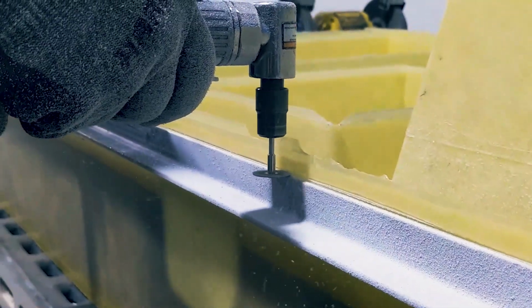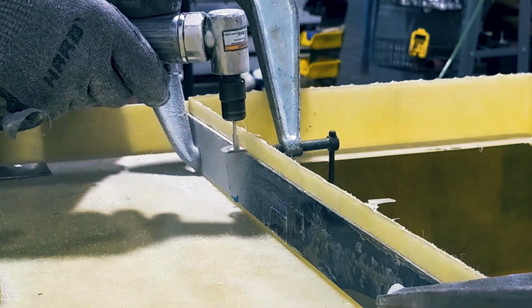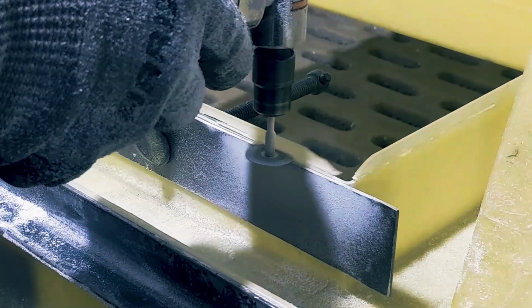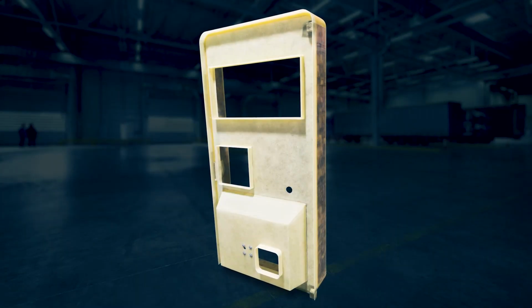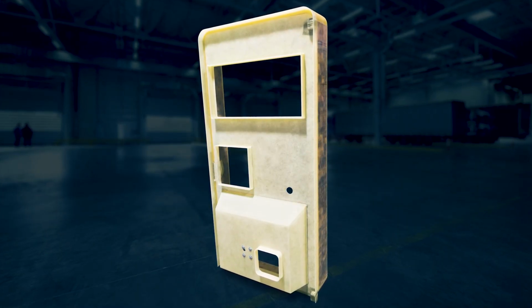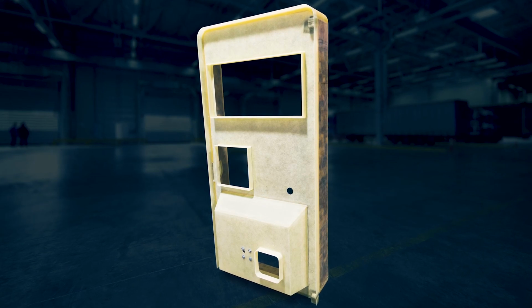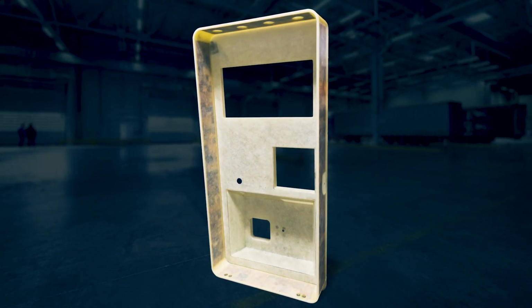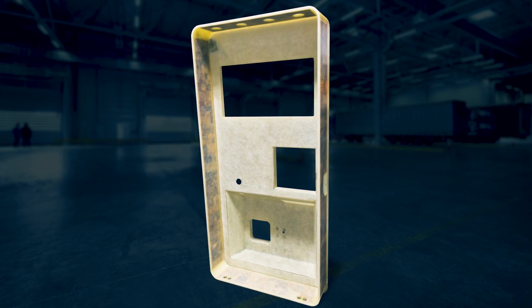We then trim the vertical flanges using the machine tooling scribe lines, and the part is finished and ready for painting. This composite enclosure door was able to meet all geometric surface and stiffness requirements at only 32 pounds, less than 40% of the original weight of the metal enclosure door.